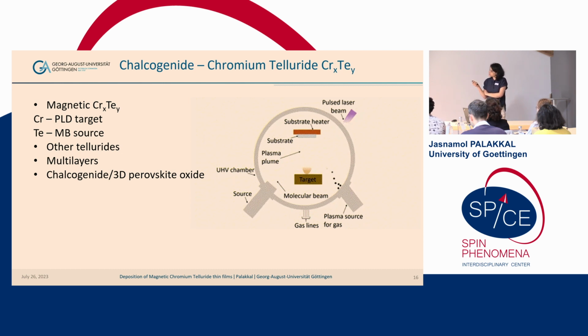So here we are growing chromium tellurides. We selected chromium telluride as the first material because it's also magnetic. And in this case, we are providing the chromium from the PLD target and tellurium from the molecular beam source.